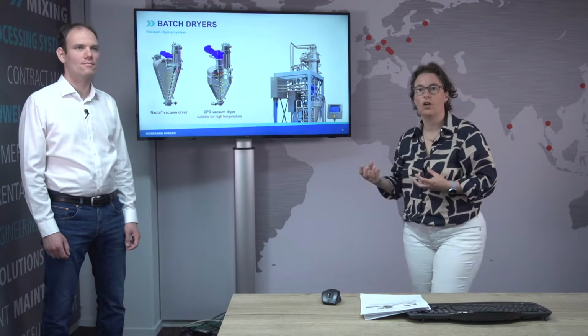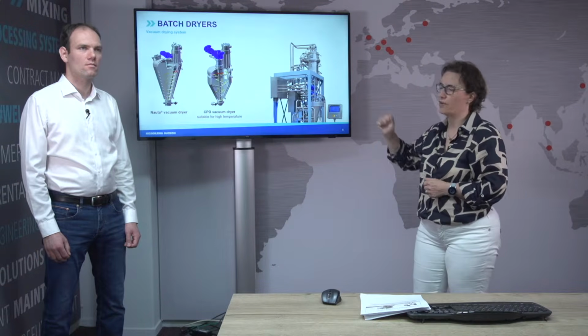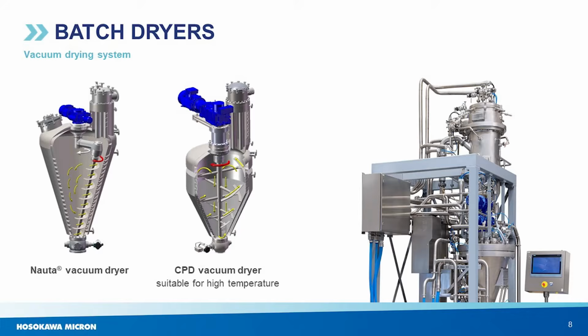If we need to achieve lower moisture contents, we can make use of our batch dryer. We can also use it for smaller production capacities. We have a vacuum dryer, the Nauta dryer, or the central paddle dryer, which can also operate at higher temperatures. Temperatures of 325 degrees C in combination with full vacuum ensure that even the difficult volatiles will be evaporated, and we can go to ppm levels.